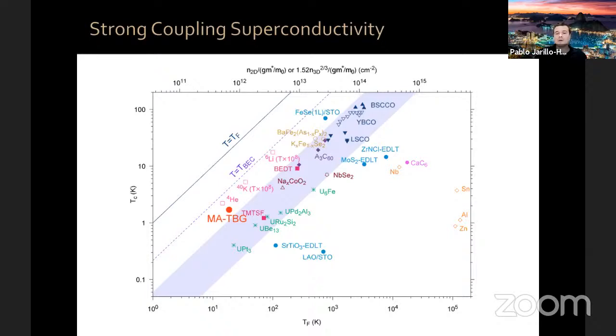Now, we have performed experiments that I have not shown here, but the results are already in the arXiv, where we show that TC is highest in the region where there is a minimum in the density of states. So it's certainly not weak coupling BCS superconductivity with the formula where if you have a high density of states, you get higher TC. It's the opposite, actually. TC is the highest when the density of states is the smallest, okay?